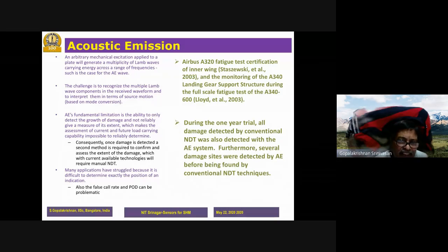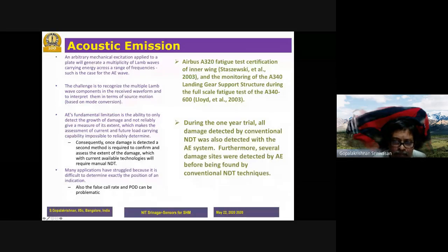However, having said that, they have used this for a variety of applications. In the Airbus A320, the fatigue test certification was done using acoustic emission. During the one year trial, all damage detected by conventional NDT was also detected by the AE system. You need to have another system to corroborate the results from AE. Furthermore, several damage sites were detected by AE before being found by conventional NDT. So this is a very robust method, but you need to use it with another method to confirm its results.